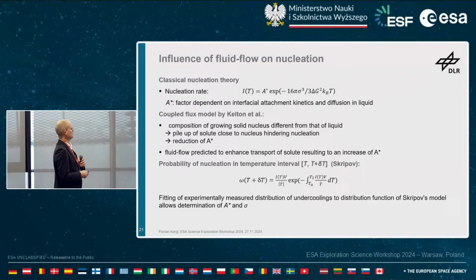So, and this predicts a reduction of this pre-exponential factor for systems that show this behavior. On the other hand, if you have fluid flow in the system, then during solidification, this is predicted to enhance the transport, similar to what we have seen with the iron boron system, where we were transporting, let's say, the iron with fluid flow towards the growing interface. And in the same way, this could work for the nucleation.